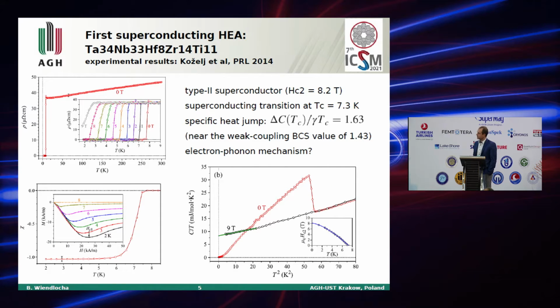So the first superconducting high entropy alloy was discovered in 2014. That was an experimental work, and you can see the transition to superconducting state here in resistivity, susceptibility, heat capacity. So it looks like a typical BCS-like superconductor. Critical temperature was around 7.3 Kelvin. It had a specific heat jump corresponding to a little stronger coupling than assumed in the weak coupling BCS theory.